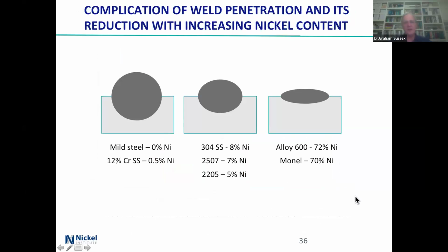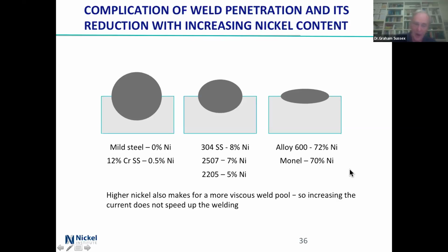One little complication is if you're swapping from one metal to another, then look at what happens with more nickel or less nickel. So mild steel and 12 chromes, lots of penetration because there's very little nickel. 304, 2507, 2205, same sort of band, that much penetration. And the really high nickels, not much penetration at all. And higher nickel also makes a more viscous weld pool. So increasing the current won't speed up the welding no matter what you do. You just get too much heat in, you'll get it too hot, and then you'll wind up with other problems.